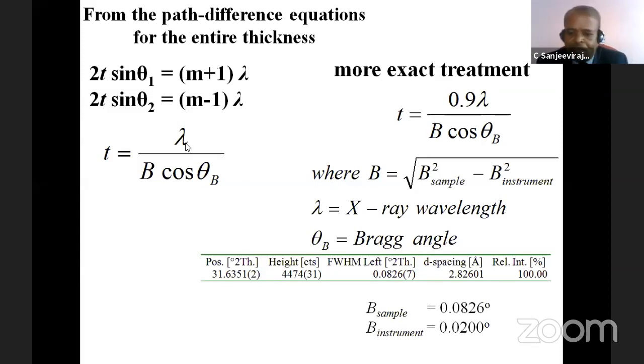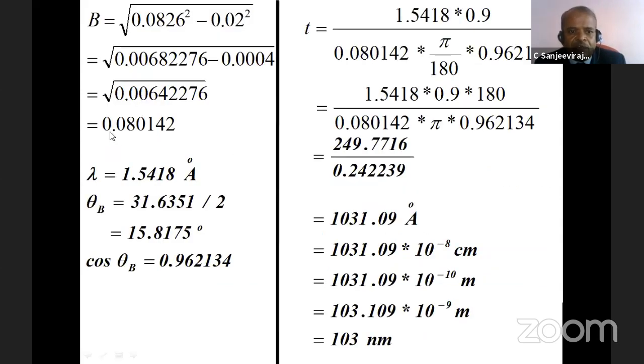In this way, we can have this typical data, and through that data we can measure these full width at half maximum values. This is from the sample, and this is due to the instrument. You take the correct value for your sample, substitute this data, and finally I can evaluate it. The value is 103 nanometer. In this way, we can measure the size of nanocrystalline materials.